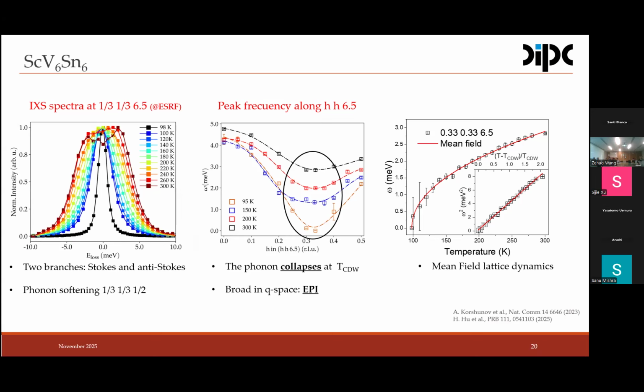And then when we cool down, we actually can track the softening of this L 1/2 mode towards zero energy. If we plot the temperature, the momentum dependence of this 1/3, 1/2 phonon, we actually see that the phonon is not flat. There is a small, actually broad softening already visible at room temperature, due to perhaps already substantial electron-phonon interaction at 300 Kelvin. If we then cool down, and we track the momentum dependence, we clearly see how the phonon softens at the 1/3, 1/2 propagation vector. So the phonon, from our data, we see that it actually collapses.